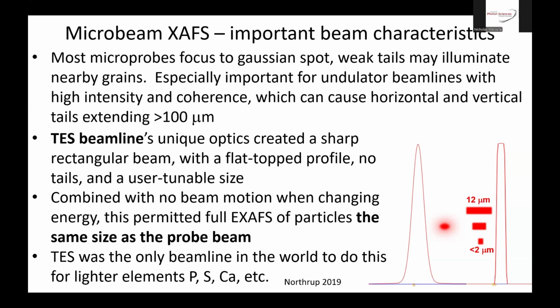So if your tails reach that, you'll be seeing that instead of what you think you're looking at. And this is more important, especially on insertion device undulator beamlines, because the high flux and coherence often creates particularly long tails in the horizontal and vertical direction, like a cross. And those can extend sometimes more than 100 microns from the central spot. And they can wreak havoc with spectroscopy if you're looking at low concentrations.